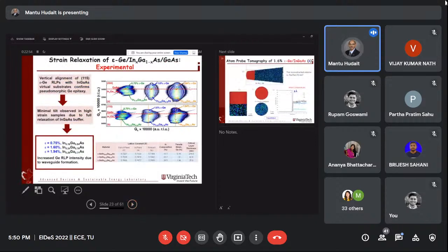And what you are noticing, maybe one of them I can go through. Right-hand side, 1.94%. That's called a reciprocal space map. It has an X-ray unit. The X-ray unit has a pixel detector. I'm pretty sure you have that. You might have a powder or thin film. And then every contour represents every material. This is gallium arsenide. The middle top is the strained germanium. The bottom is the InGaAs.